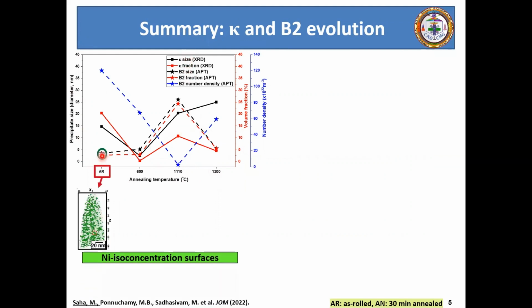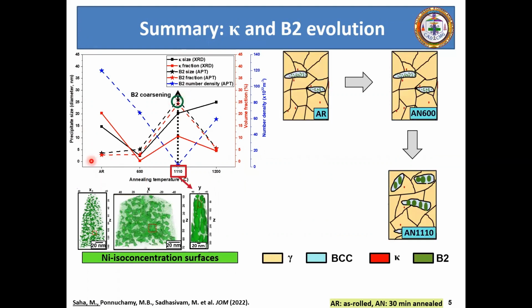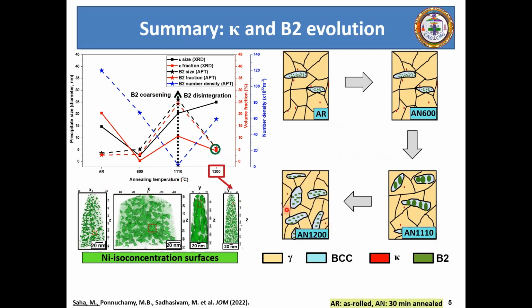And what we can interestingly observe is that from the as-rolled to 600 degrees to 1110 degrees, there is an increase in the size of the B2 precipitates with a decreasing volume fraction and a decreasing number density, which implies that we have the coarsening of the B2 precipitates between the as-rolled and the 1110 degrees annealed condition. On the contrary, when we further expose the material to a higher annealing temperature of 1200 degrees, we see a decrease in the B2 precipitate size or diameter, but with a concomitant increase in its number density, still localized within the BCC phase. So this means that there is a disintegration undergone by the B2 precipitates from the 1110 to the 1200 degrees annealed condition.